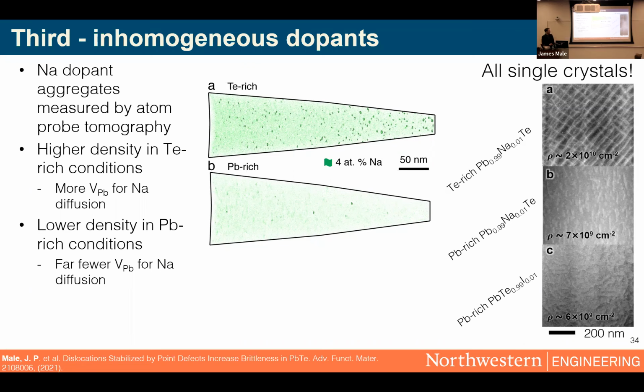If we actually look at the analog that's in lead-rich conditions, we see that the aggregation is very suppressed. So what we believe is happening here is lead-rich conditions are essentially filling some of those lead vacancy, cation vacancies, and lowering the diffusion and mobility of sodium through the material. And also just by quick visual inspection, we count more dislocations in our tellurium-rich P-type samples as opposed to the lead-rich analogs or N-type doped samples. So clearly there's all these interactions that are even just putting more dislocations in our material before we try to deform it further.